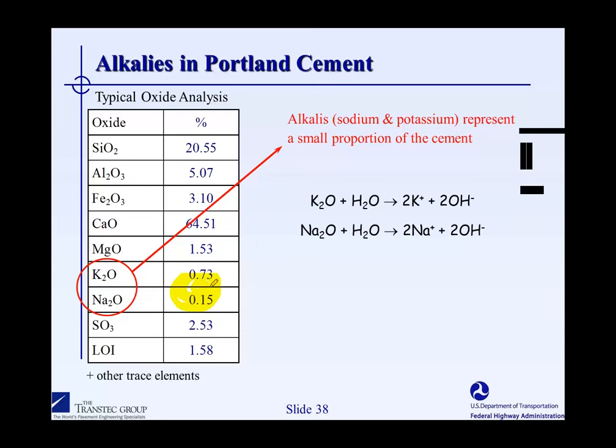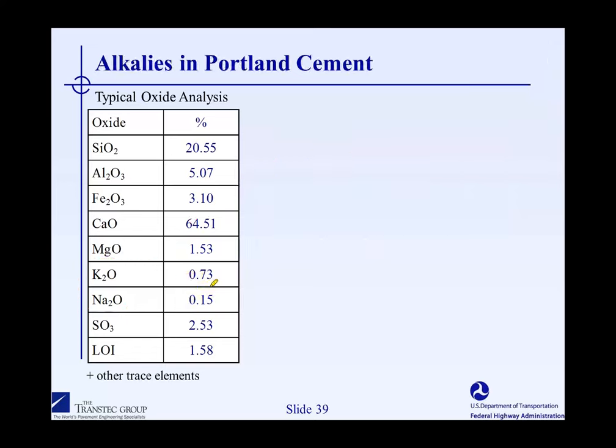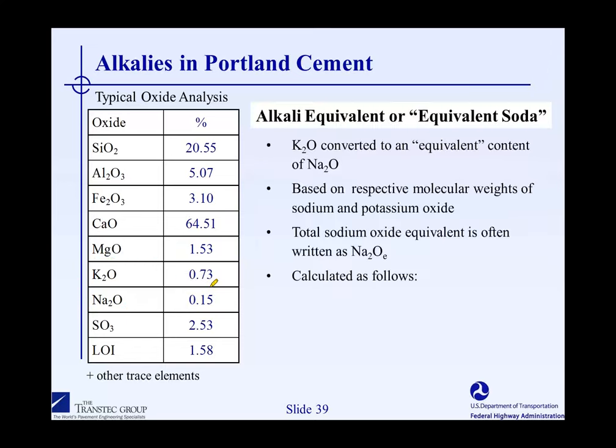And as we discussed before, the pore solution, after 24 hours, is composed almost entirely of potassium, sodium, and hydroxyl ions. So despite the fact they're only present in very small amounts, they dominate the pore solution, and there's enough of them to raise the pore solution pH to an excess of 13. So they are important.